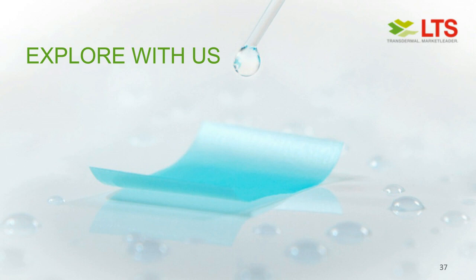So the next question is, what is the average drug loading? Looking back at the oral thin films which have been commercialized, they're in the range of, I would say, 20 to 30 milligrams drug loading. We are pushing the boundaries a bit higher than that. Depending on the API and the type of OTF, I would say the range of 50 to 100 milligrams would be the upper limit, not the typical one. Typically, you try to be lower, of course, if possible.